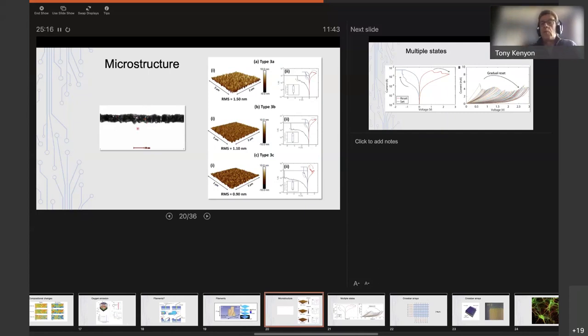And we've turned the contrast way up, so the top electrode and the bottom electrode are completely saturated. But what we can see is there's some structure here in the oxide. We can first of all see that there is a rough bottom interface and a rough top interface, which is not typical. We deliberately made these rough. If you were making a CMOS device, you would want that to be very flat. And we can see these vertical lines that seem to come out of regions where we have these valleys in the bottom electrode.